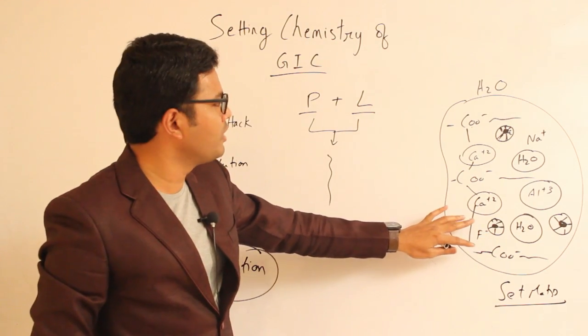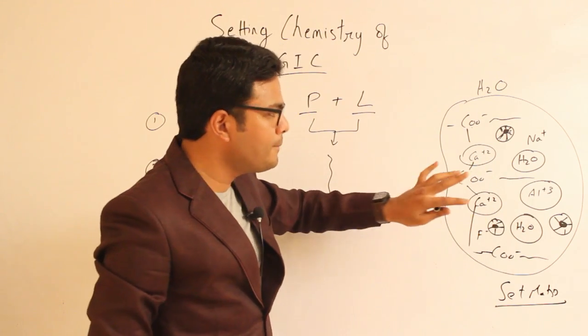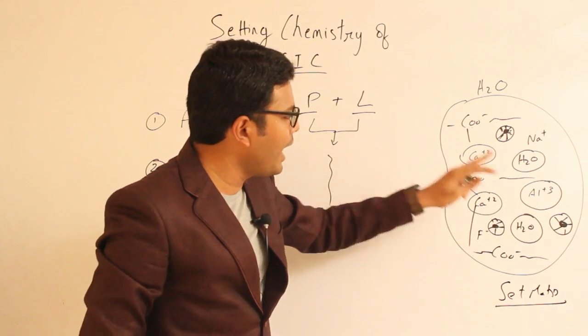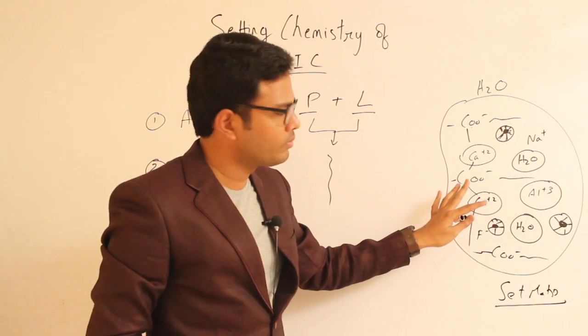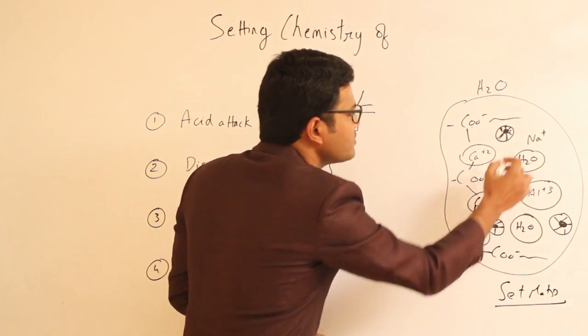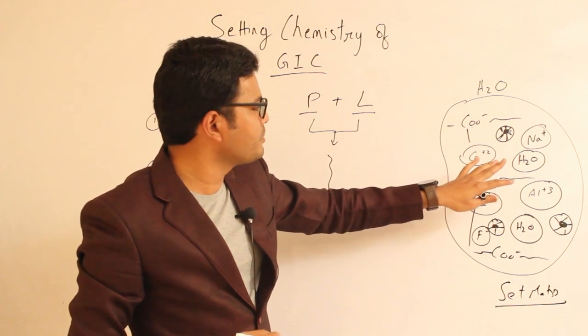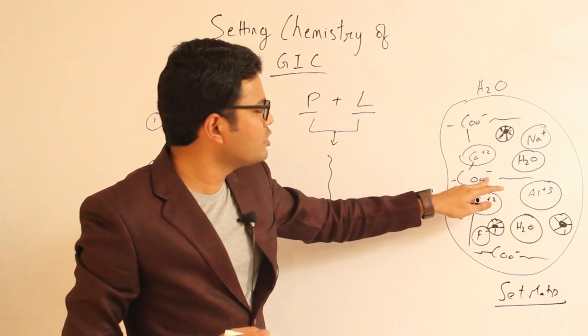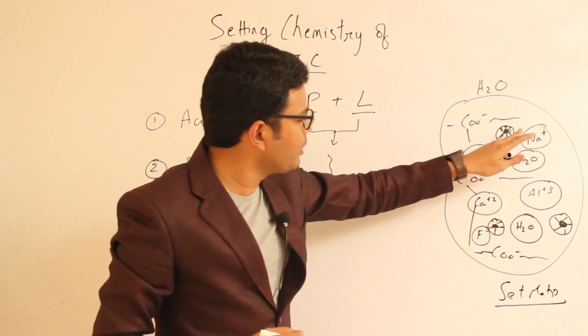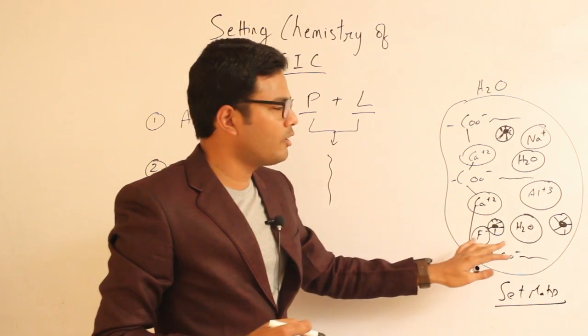This entire set matrix is a combination of unreacted powder particles surrounded by silica sheath, embedded in a hydrated amorphous matrix made up of calcium and aluminum poly salts. Apart from these ions, we have fluoride ions and sodium ions. Few sodium ions participate in cross-linking by replacing hydrogen present in the carboxylic groups, whereas the rest of the sodium and fluoride ions are uniformly distributed all over the matrix.